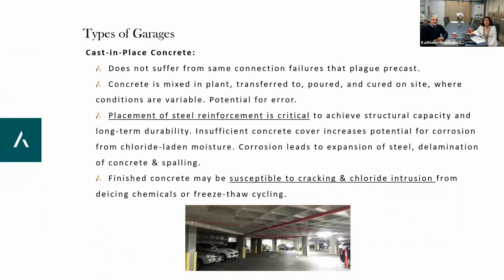We have cast in place concrete, which is probably the most common that's being built right now. It does not suffer from the same connection failures that plague precast. The concrete's mixed in a plant, but then it's transferred to and poured and cured on site, where the conditions are very variable. So there's a lot of potential for error. Time is money. Construction happens very quickly. I can tell you, we've been on many sites where the rebars are rolling against the base of the formwork, and you have inappropriate concrete cover. And so those are the structures that I'm going to break down the fastest.